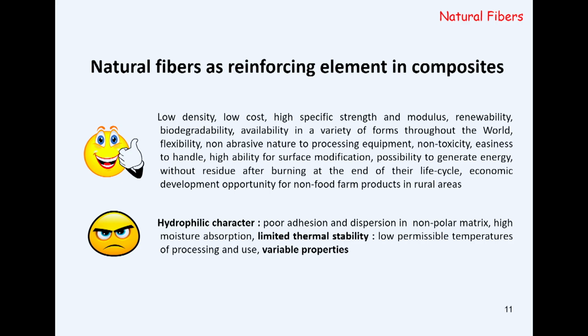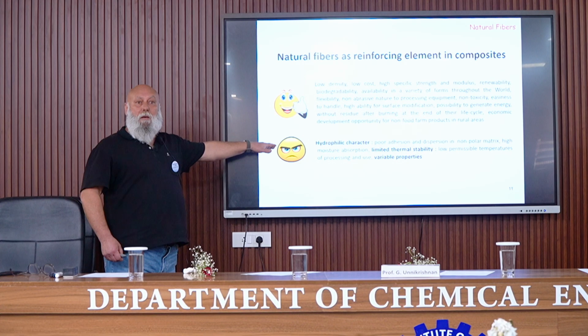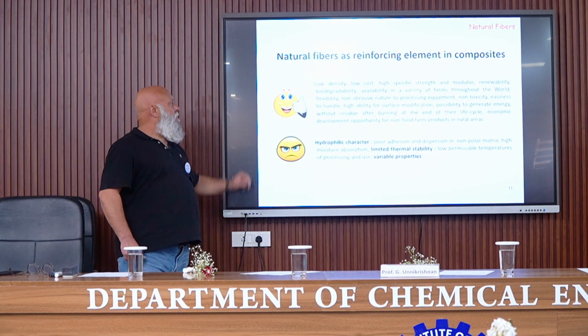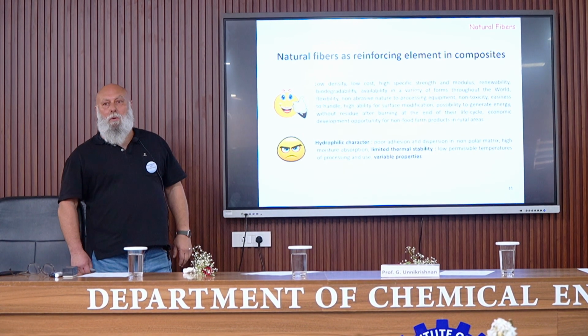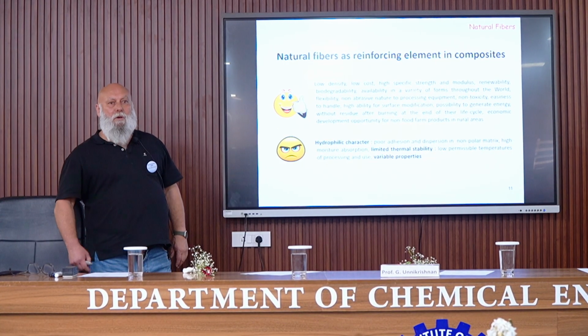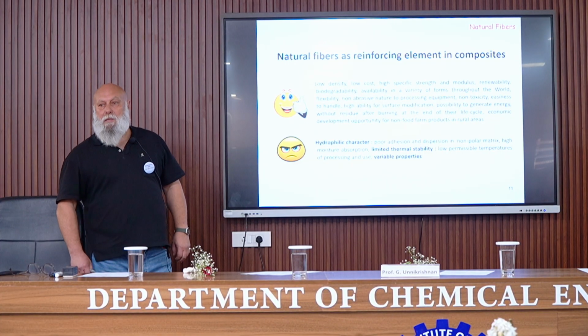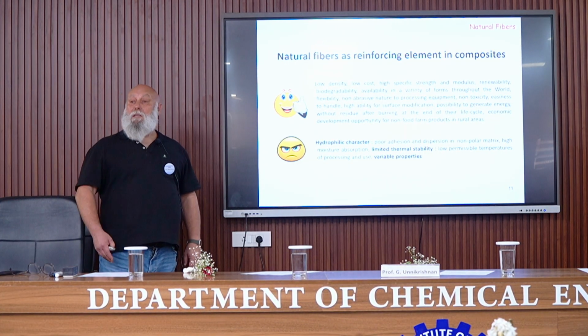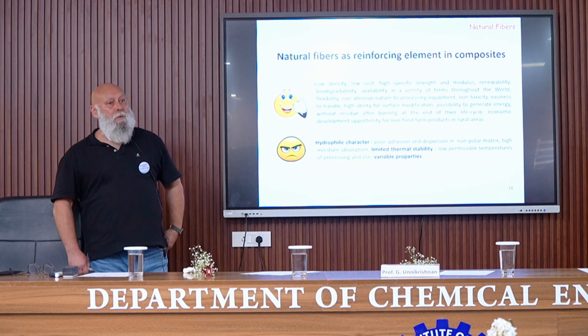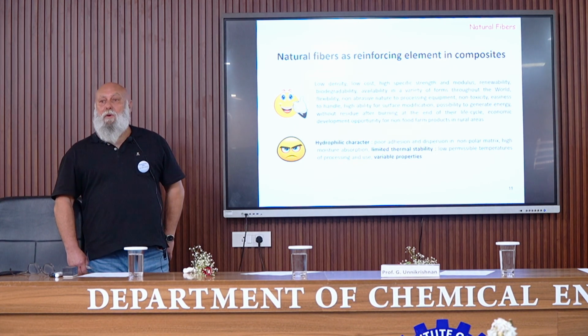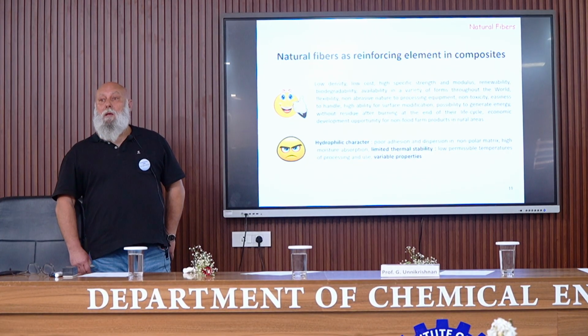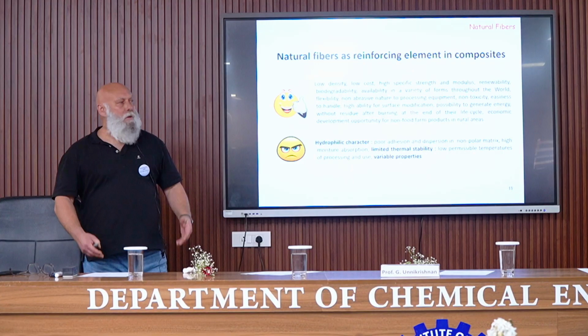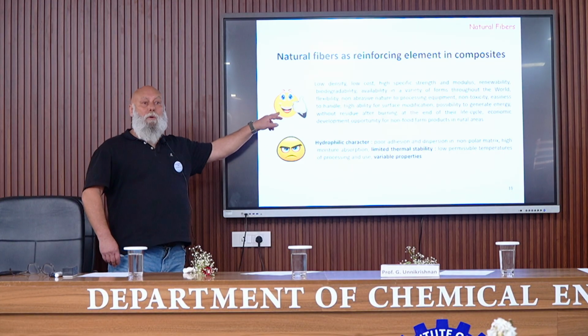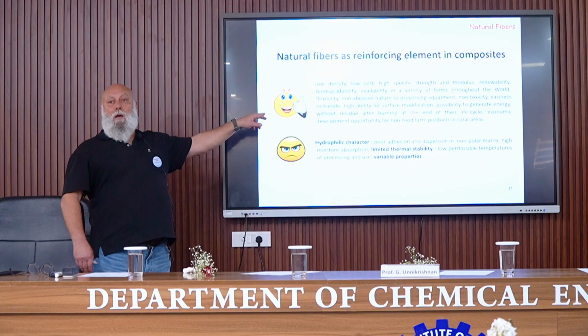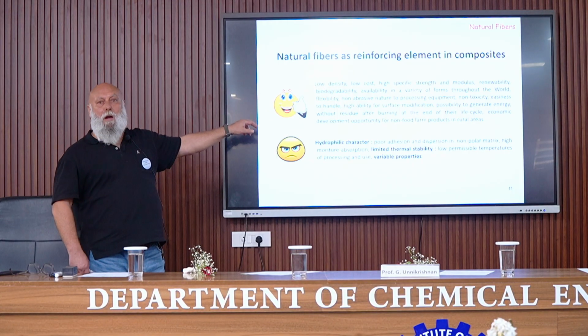I report here the most important advantages. Of course, there are some drawbacks also. The first advantage is the density, which is low. Typically, for natural fibers, it's between 1.3 and 1.5 gram per cubic centimeter. If you compare to glass fiber, which is broadly used for composite manufacturing, the density of glass is 2.5 gram per cubic centimeter. So it's a lighter material. It's also a low-cost material because in some cases, byproducts from the agricultural industry can be used.